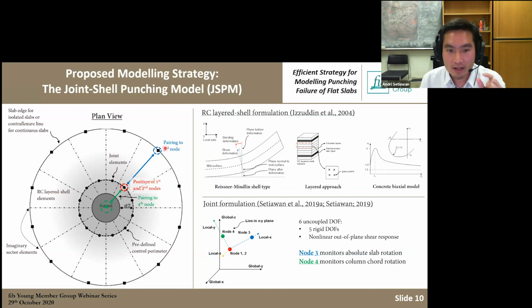If we subtract the rotation that I got from node 3 and node 4, we can get the relative slab-column rotation, which is used by the critical shear crack theory to calculate the resistance. So the idea is that every load step, these two nodes, node 3 and node 4, will monitor and save the rotation, and then I can subtract them internally in the algorithm in order to check the remaining resistance that I have at that current step, and then I can determine whether the punching has occurred or not. So it's an iterative scheme.